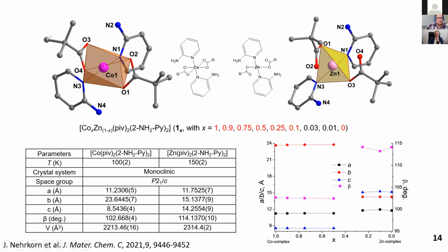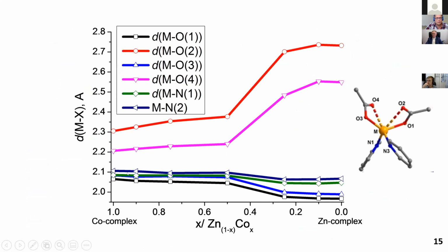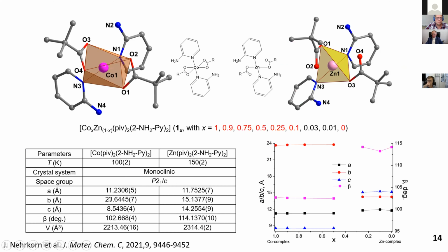Here you can see this cobalt complex in an octahedral environment of 4 oxygen atoms of 2 carboxylate groups and 2 nitrogen atoms of 2 pyridine amino ligands. On the other side, you can see the tetrahedral complex of zinc. It's tetrahedral as a result of elongation of the zinc-oxygen distance of the 2 carboxylate groups. These compounds are not isostructural. They crystallize in the same space group, but with different cell parameters.